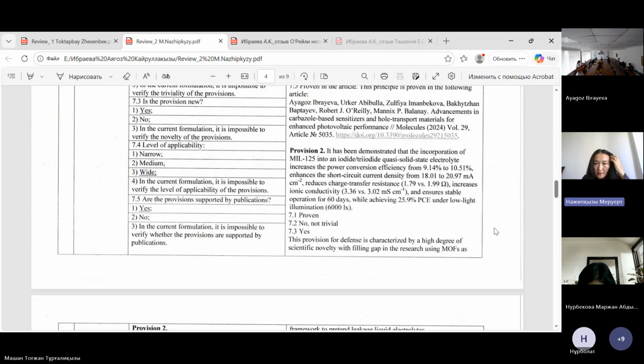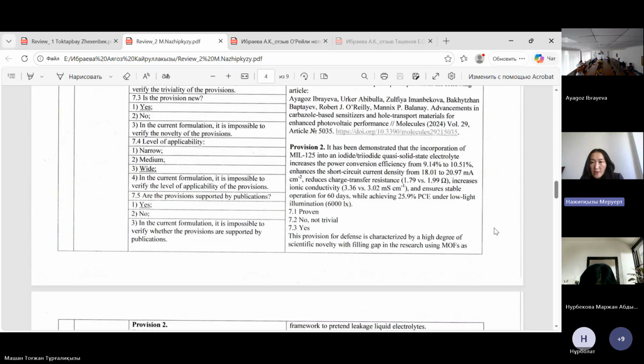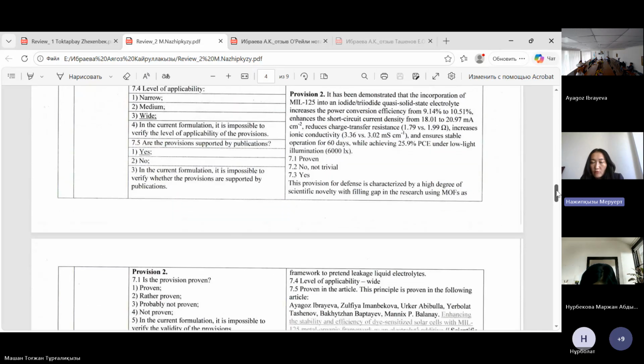Next, the second provision. It has been demonstrated that the incorporation of MIL-125 into an iodide/triiodide quasi-solid-state electrolyte increases the power conversion efficiency from 9.14% to 10.51%, enhances the short-circuit current density from 18.01 to